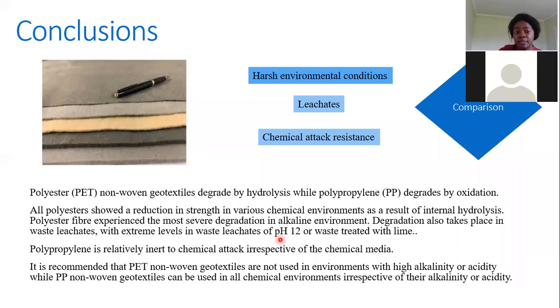So in conclusion, we found out that polyester degrades by hydrolysis and polypropylene degrades by oxidation. While all polyesters showed a reduction in strength, polypropylene was relatively inert to chemical attack. So we recommend that polyesters should not be used in high alkalinity or high acidic environments, while polypropylene can be used in all environments, irrespective of the chemical nature.